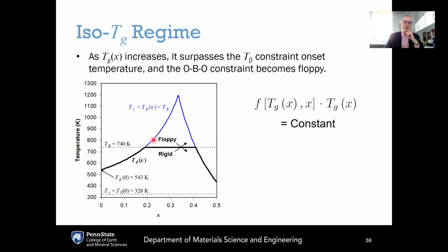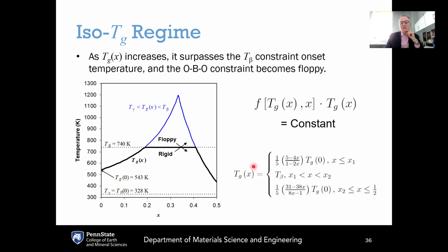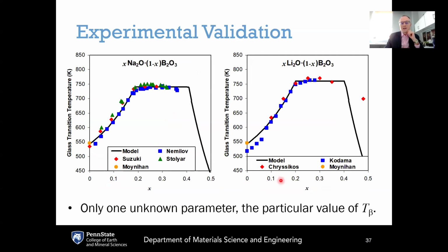And so instead of following this blue curve, basically we follow the black curve where the Tg rises until it hits T beta. Then it gets stuck at T beta until there are enough non-bridging oxygens for the glass transition temperature to go back down again. That gives us this final equation for the glass transition temperature as a function of x, where basically we need to know what Tg of 0 is. This is the measured glass transition temperature of B2O3, and then we need to know what T beta is.